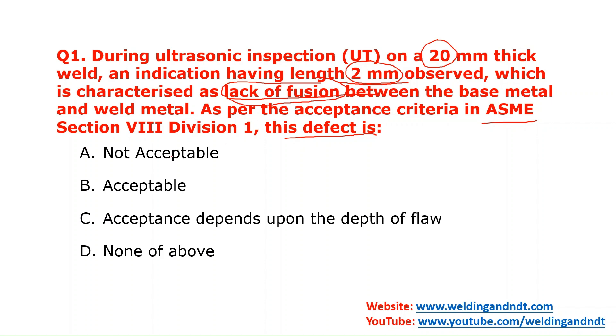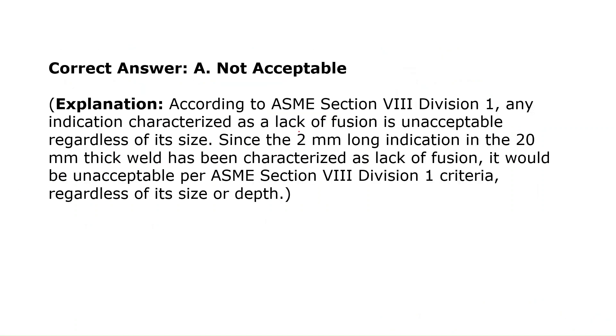As per ASME Section 8 Division 1, this will not be acceptable. Any kind of crack, lack of fusion, or lack of penetration is not accepted as per ASME Section 8 Division 1. So the correct answer is option A — according to ASME Section 8 Division 1, any indication characterized as lack of fusion is unacceptable.